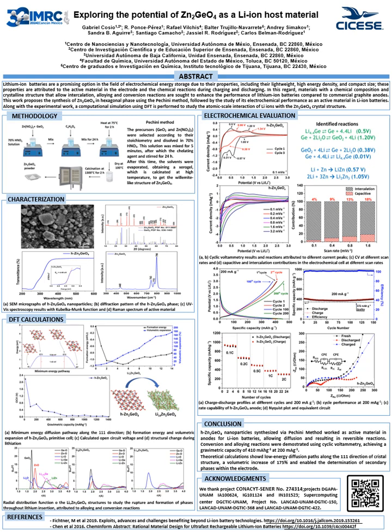The initial results from cyclic voltammetry revealed intense current peaks during the first cycle, attributed to the formation of the solid electrolyte interface and initial reactions. Following this cycle, we were able to identify alloying and conversion reactions for each observed peak. Additionally, studying voltammetry at various scan rates allows us to calculate the capacitive contributions of the electrode. These contributions arise because the nanostructured material has a large surface area, facilitating ion interactions with the surface.